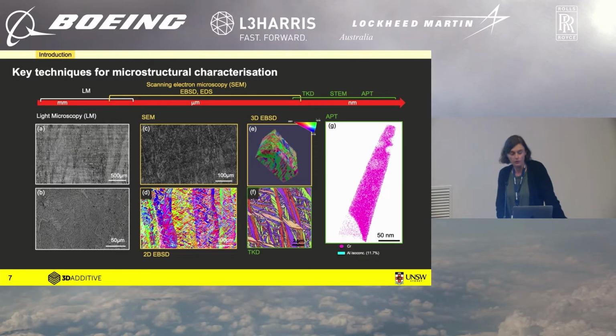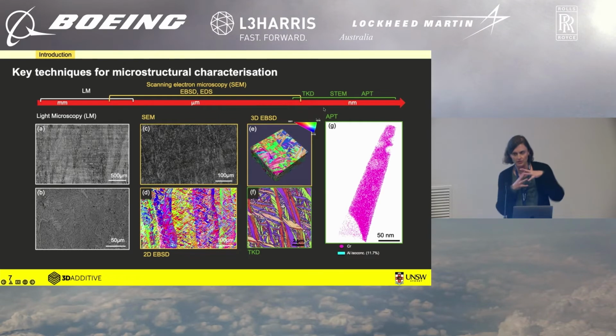The key for all of that, as I said, is microstructure characterization, and we do a lot of microscopy. And I mean, don't worry about the details here. What I just want to show with this slide is that we need a bunch of correlative techniques, and they range across several length scales, because these microstructures are highly hierarchical, and that's how we achieve amazing properties. So we can use light to, on the left-hand side here, show grain and dendritic structures. We can use electrons to sort of go to the micrometer towards the nanometer scale. We can extract crystallography information. We can extract information in 3D.